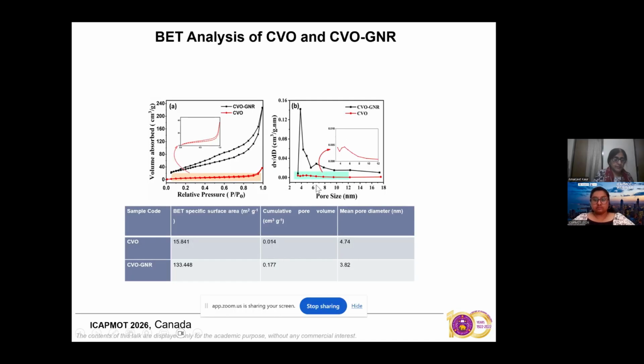So we can see that by addition of GNR, the BET surface area of the pores has increased by an order. Then the cumulative pore volume also increases, and the mean pore diameter also reduces. So these are very good characteristics for the CVO GNR composite, which will be more suitable as compared to pure cobalt vanadium oxide.